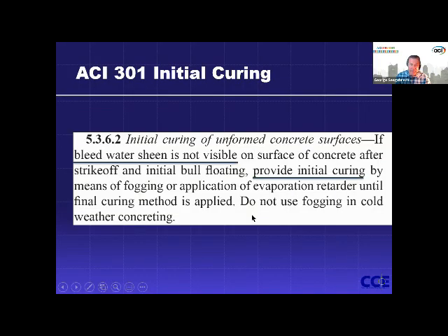Did I freeze here? No. Okay, so we already talked about initial curing. Those are the things probably before, when the concrete is still plastic. So this might be fogging when, say, with the silica fume mix, it's very hard to see the bleed water coming up because of that high fine surface area of silica particles. And if you have a high rate of evaporation, it might look dry.